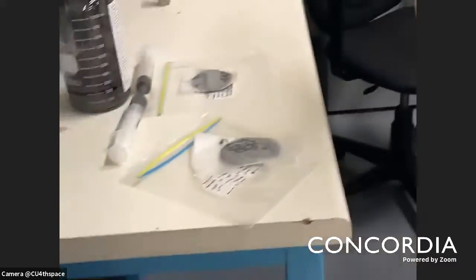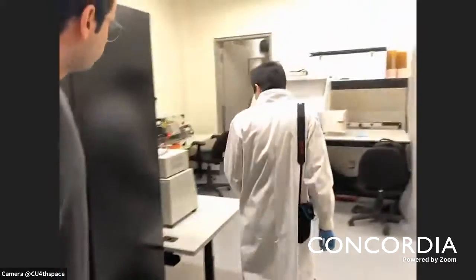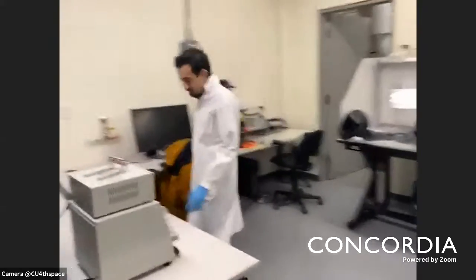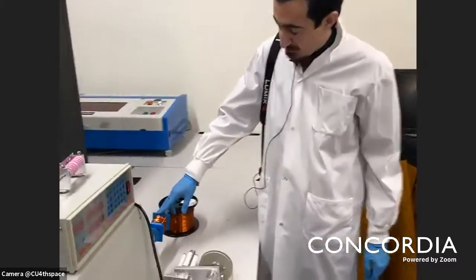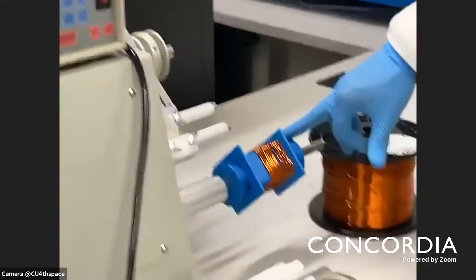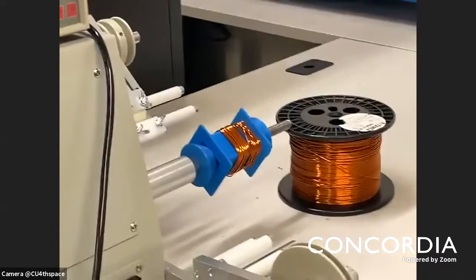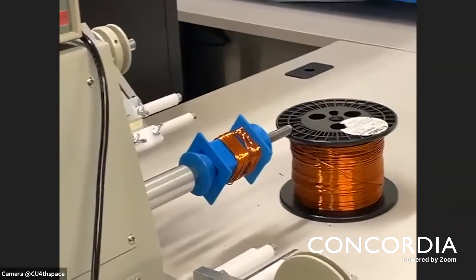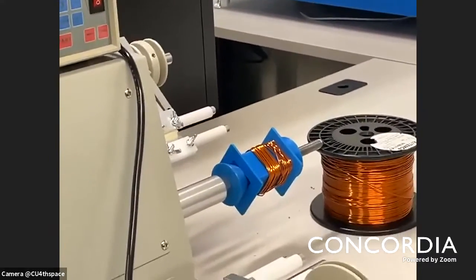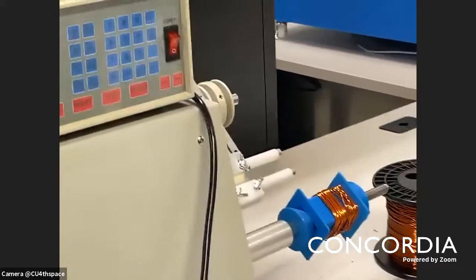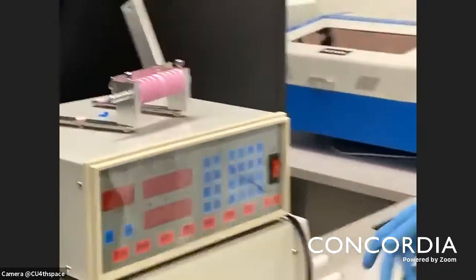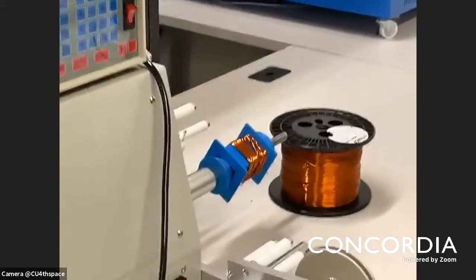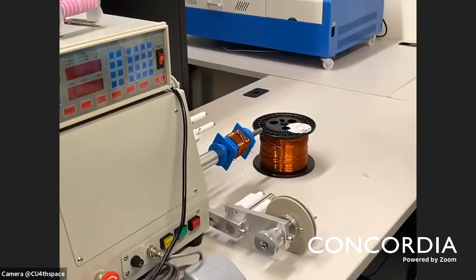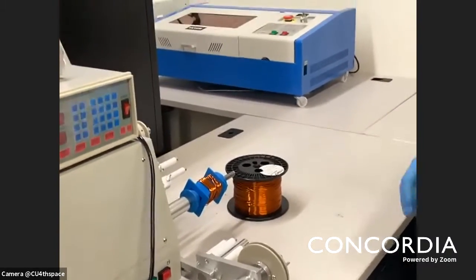Here we have a kind of winder that we are using for the coils. As you know, the stimuli can be a permanent magnet or an electromagnet, but with a permanent magnet you don't have control over the amount of the magnetic field. By using an electromagnet, you can control the current that passes through the coil, so you have control on the magnetic field, and you can have a better response from your MRE or MRF.